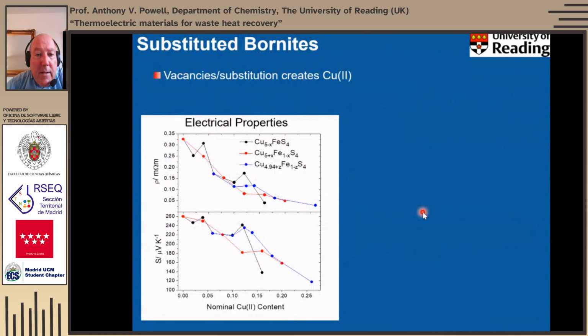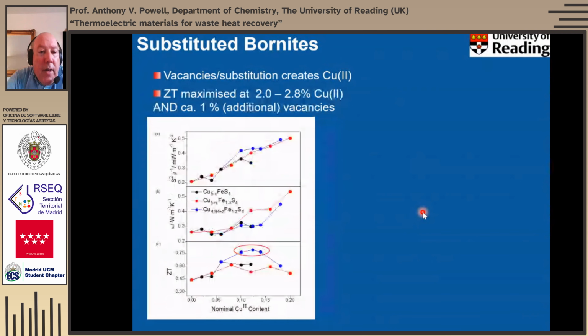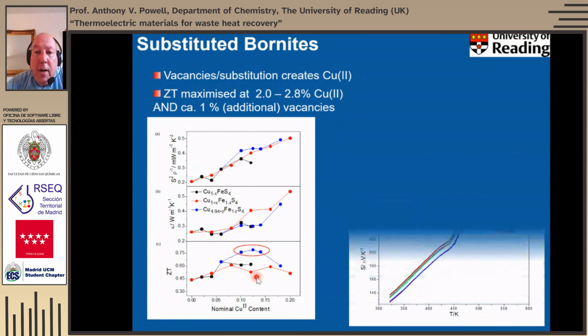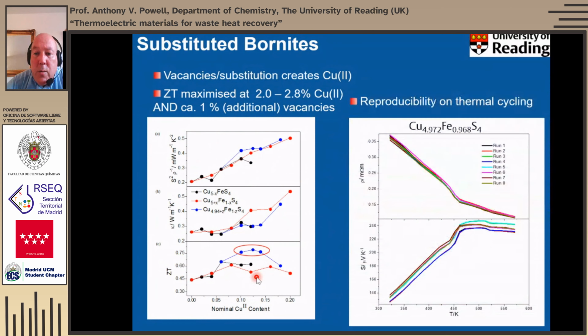Interestingly, the electrical properties and the Seebeck coefficients, regardless of which series we take, so these are the three different series I've just mentioned, seem to follow a common curve. And in fact, the power factor seems to scale almost linearly with the copper 2 content. So each time we're doing these changes, we're trying to modify the copper 2 content to introduce some more holes. We see that we increase the power factor in an almost linear fashion with the copper 2 content. However, to get the maximum performance, this is where we get the highest ZTs here, it's important that we don't just have the optimized copper 2 content, which is about 2 to 3%, but we also need those additional vacancies.